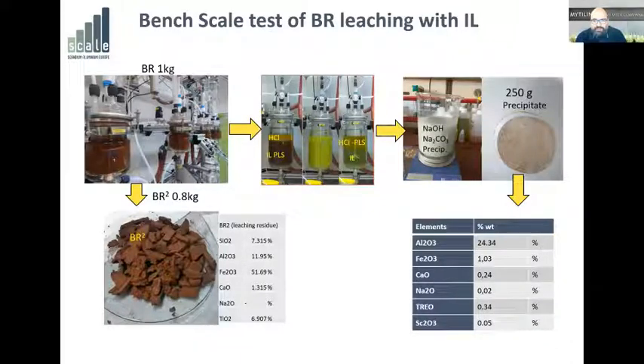But you can see how much less the volume of the new pregnant liquid solution is in the case of hydrochloric acid in regards to the ionic liquid. So we took that, we made a precipitate out of it, and you can see we got a precipitate that had 0.05% scandium, and a bauxite residue, a leaching residue, a bauxite residue squared, if you want, which was now enriched in iron and depleted in soda. This was a nice technology.